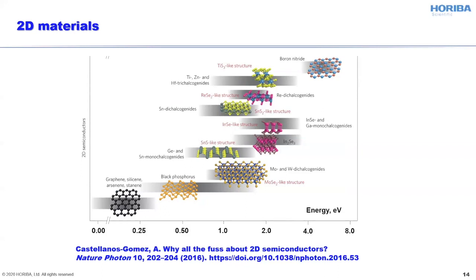The nice and great thing about this diversity is that these two-dimensional materials cover the whole spectrum of properties, from semi-metallic or metallic, like graphene or some transition metal dichalcogenides, and then narrow band gap semiconductors, modest band gap semiconductors, and all the way up to good dielectrics like boron nitride. So in the family of two-dimensional materials, we can pick pretty much anything we want in terms of the band gap width and the nature of that band gap, in terms of whether the semiconductor is direct band gap or not.